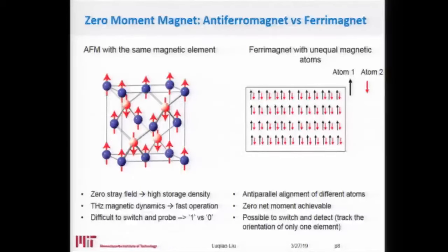At the same time, we can also consider another group of magnetic materials, which is ferrimagnets. It also has two spin sublattices, and those two spin sublattices are also antiparallelly coupled with each other. But the difference between those two groups of materials is that for ferrimagnets, the two spin sublattices are composed of different atoms. For example, spin up is composed of atom 1, and spin down is composed of atom 2. And those two atoms can be different chemical elements, or they can just occupy different crystallographic locations. So basically, the main difference between those two materials is that this one has a lower symmetry. In the antiferromagnet, the spin up and spin down atoms are exactly the same, while in this material, spin up and spin down atoms are slightly different, although their spins are antiparallel with each other.